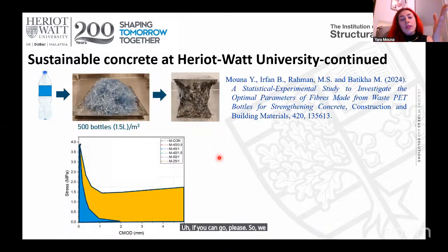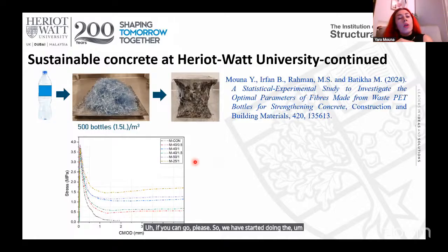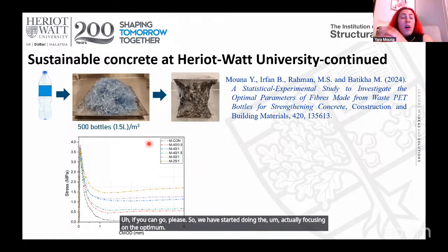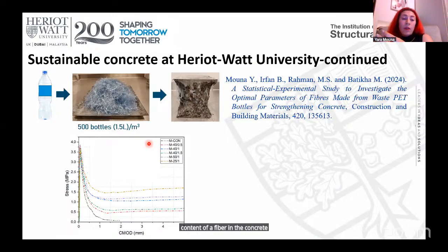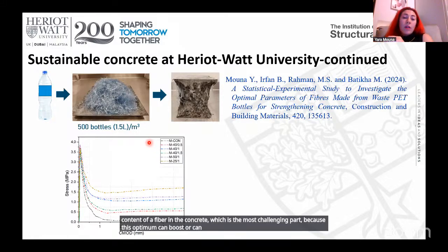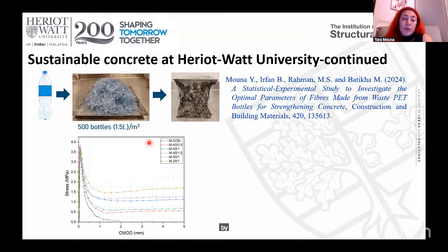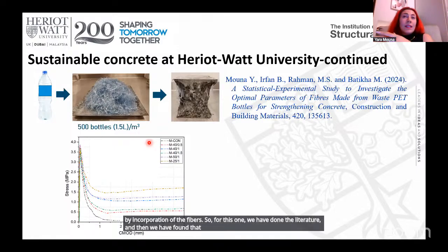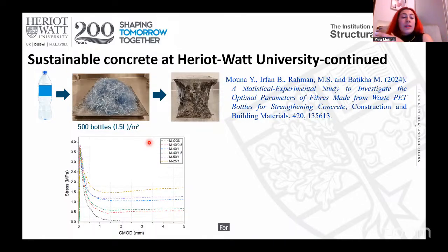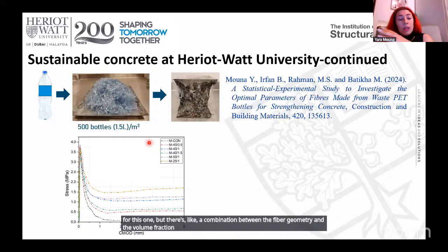So we started by focusing on the optimum content of fiber in the concrete, which is the most challenging part, because this optimum can maximize the performance benefits of incorporating the fibers. For this one, we did a literature review, and we found that the volume fraction of the fiber in the concrete was not the dominant factor, but rather a combination of the fiber geometry and the volume fraction.